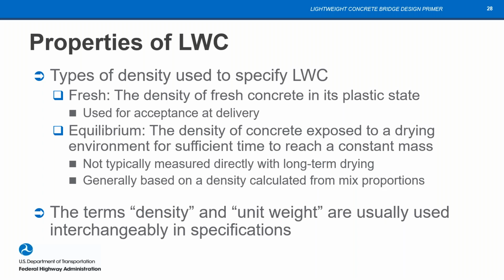There are also two types of density that we need to be sure that we use wisely when we specify densities for lightweight concrete. The first is fresh. That's the density of concrete in its plastic state when it comes out of the chute or at the end of the pump line or whatever it may be. And that's used for acceptance at delivery. But we also want to know, well, what's it going to be like a little bit later after it dries out some. Turns out that our mixes oftentimes, because they are higher performance mixes, don't dry out as much as perhaps a mix that's used for an elevated slab in a building. So we don't have as much change with equilibrium conditions as those other mixes. But at any rate, again, as I read the definition earlier, the density is the density of concrete exposed to drying to reach a constant mass. So that's what we're talking about there.